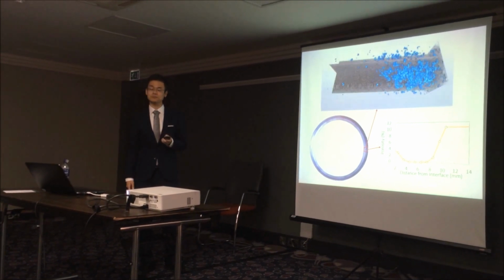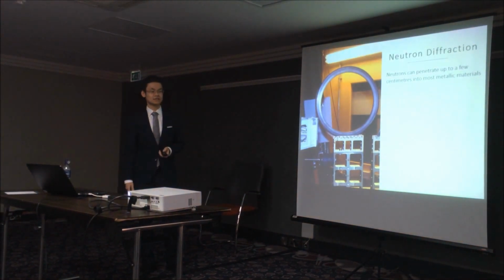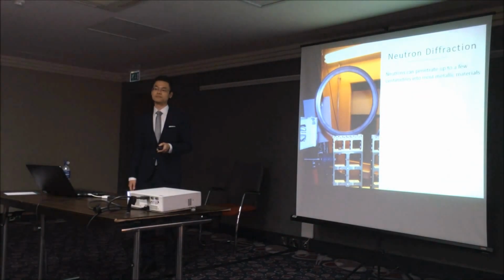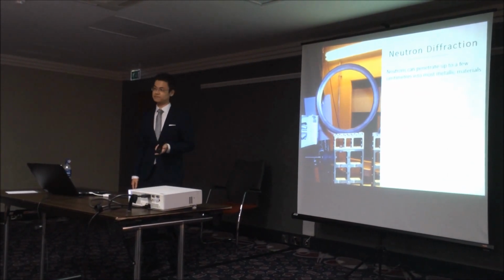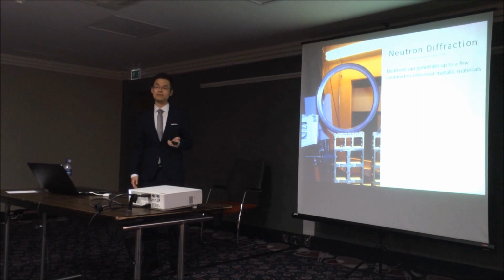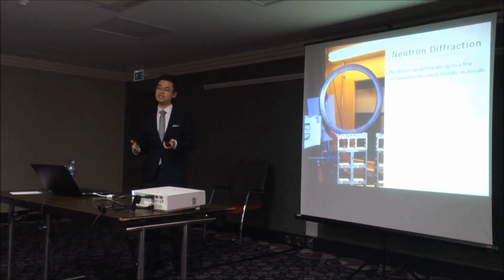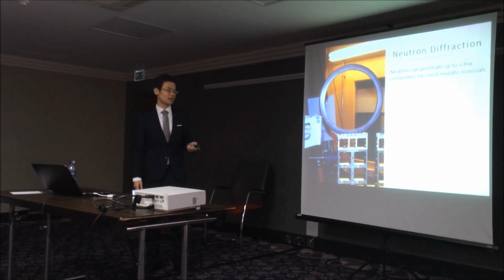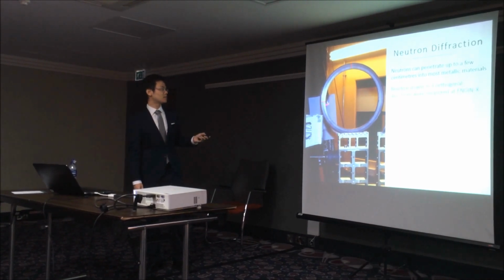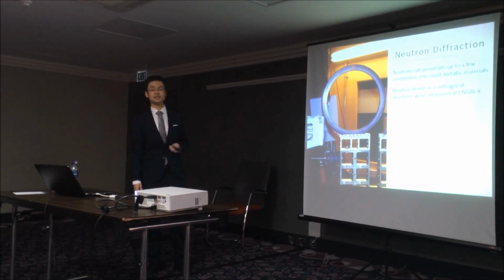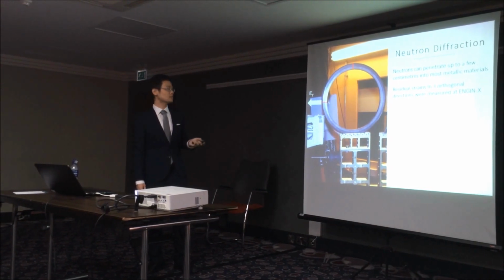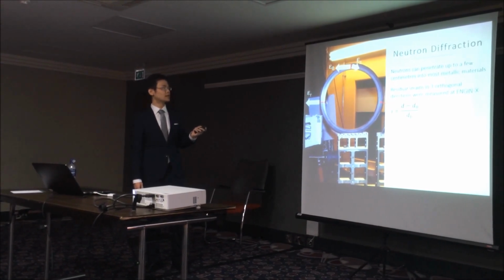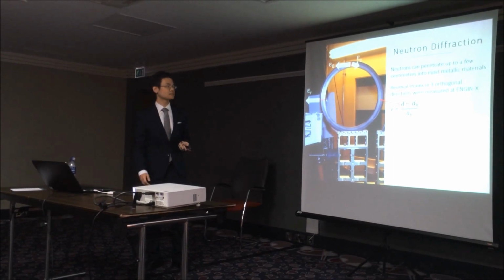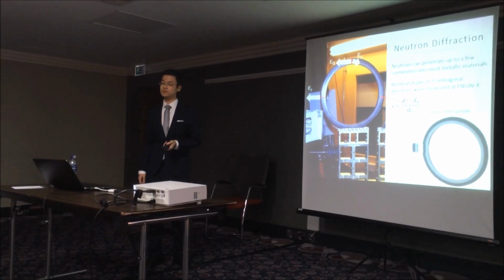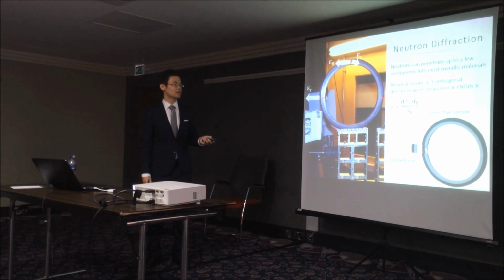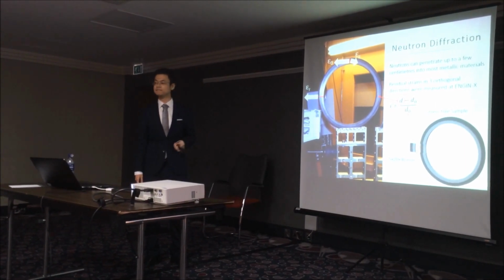Using these tomography results, we then characterized our residual stress distribution using diffraction. And neutron diffraction was selected based on its capability to penetrate into thick metallic components. Our setup at ENGIN-X measured 3 strain components across the ring thickness: the radial strain, the hoop strain, and the axial strain. The stress sample that we used was a 5 mm thick block section from a similar ring.